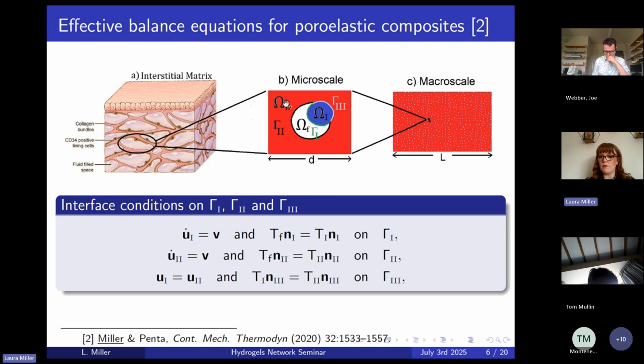I have the exact same set of conditions, but using different tensors, on gamma 2, which is this interface around here between the ECM and the pore fluid. And gamma 3 is going to be a solid-solid interface, because this is ECM and fibre, so I have the continuity of elastic displacements and the continuity of the two solid stresses in this case. That is all the equations that I need to completely describe this periodic cell and all the different elastic phases and interactions happening at that scale.